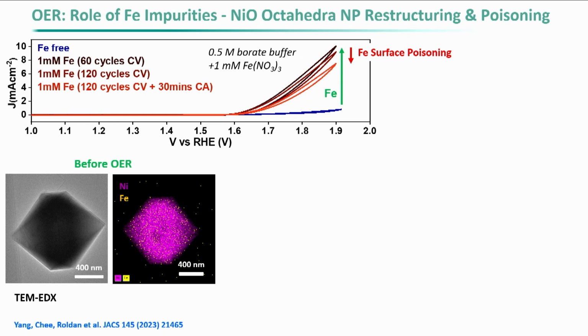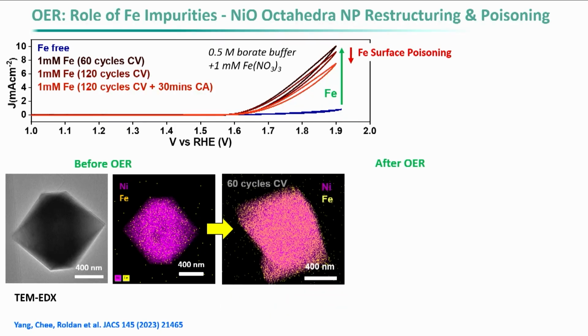So we look at this nickel oxide catalyst. This is one of the typical catalysts also for the oxygen evolution reaction. And we started adding iron, and we could make the catalyst better, but at some point we put too much iron, and you see that the catalyst starts to become worse. And now we can understand why this is. During the oxygen evolution reaction, we can see that at the beginning, in yellow, we see the iron everywhere on the surface of this electrocatalyst.